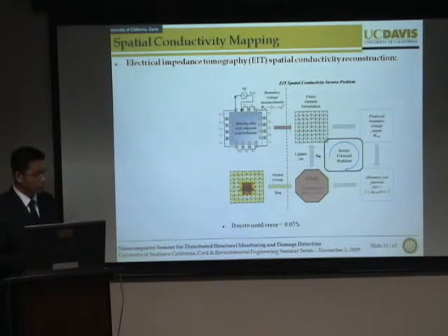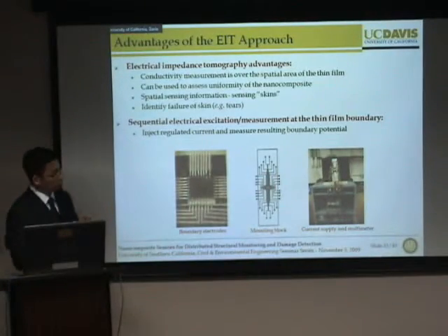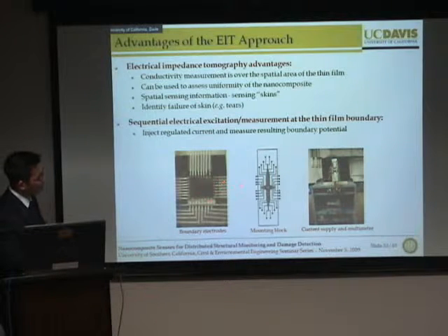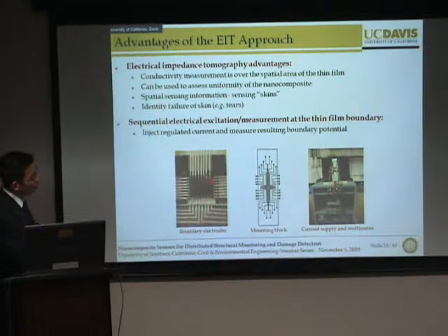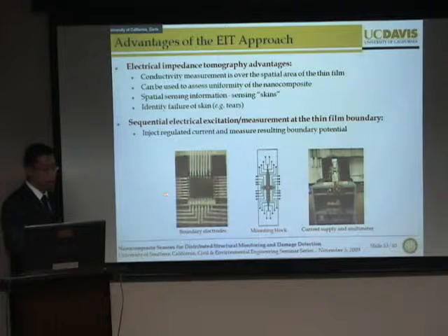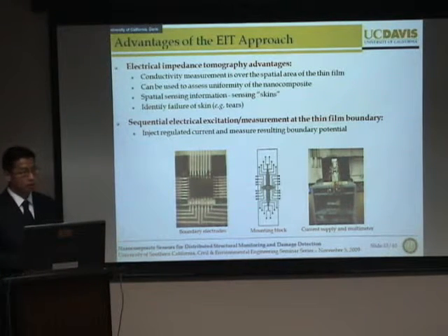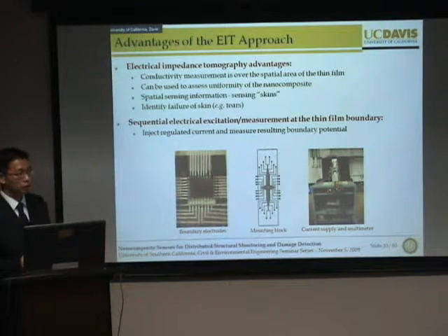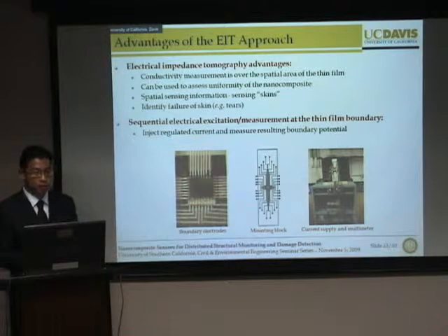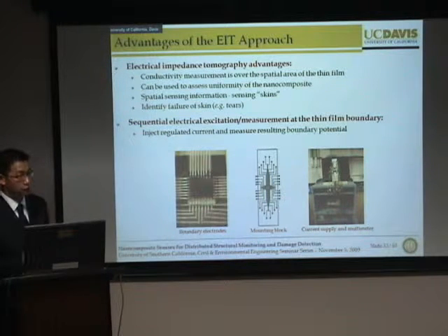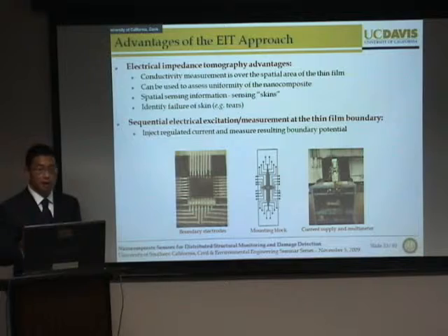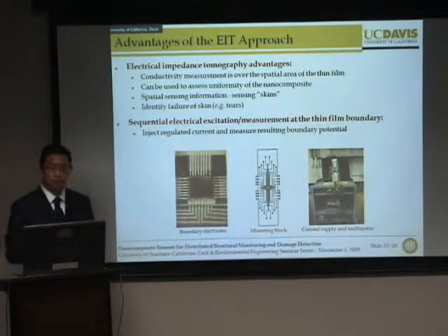Now, upon solving this inverse problem, we can then go back and output what the conductivity distribution of our material is. Now, to validate this, you can see that if we had a thin film structure, we can then easily experimentally instrument this material with a set of boundary electrodes and basically perform this experiment in the lab or in field conditions. But before we move out into field environments, we have to begin by validating this EIT technique combined with this nanocomposite system.